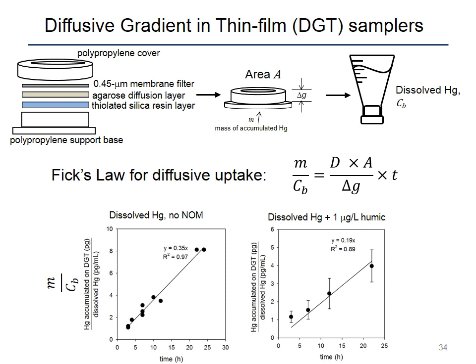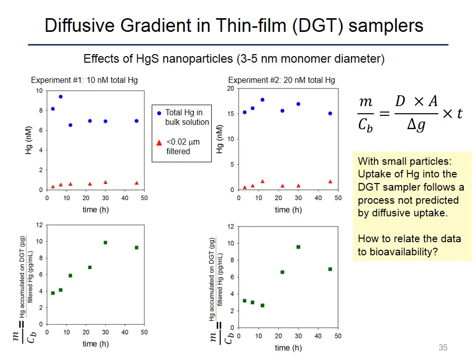But I want to say that if you have a mixture of dissolved and nanoparticulate phases, these samplers don't work as they are intended to work. So here I'm showing results of two different experiments, on the left and on the right, where we expose these samplers to solutions that comprise a mixture of dissolved and nanoparticulate mercury. Here on the top is the graph of the total mercury concentration, and what falls through a 0.02 micron filter. So we have 10 nanomolar of mercury sulfide nanoparticles spiked in here. A proportion of it dissolves. And then on the bottom, I'm showing the accumulation on the filter as a function of time. And this was done two times, shown on the left and the right.